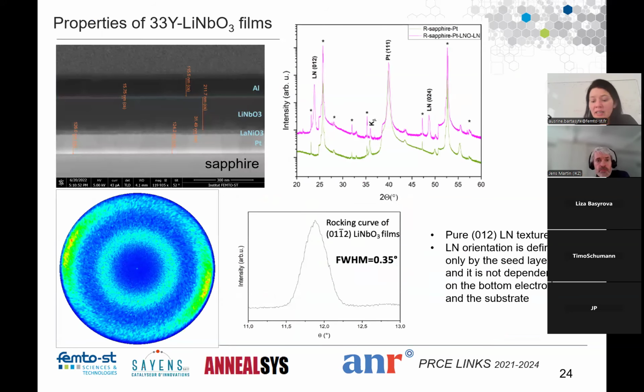And then finally, we had to abandon silicon because all the films cracked on silicon, because the thermal expansion of lithium niobate is almost 10 times higher than silicon. So it cracks very easily, even if the film is quite thin, like 100 nanometers. So we replaced silicon by sapphire just to reduce the thermal stresses. But basically, it can also be a lithium niobate substrate and so on. It can be any other substrate which doesn't have such a big difference. It can be quartz, which doesn't have such a big thermal expansion difference.